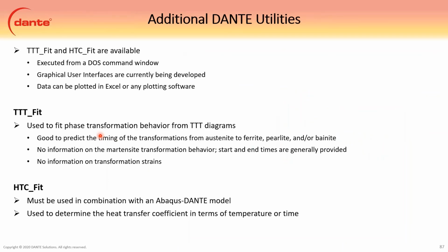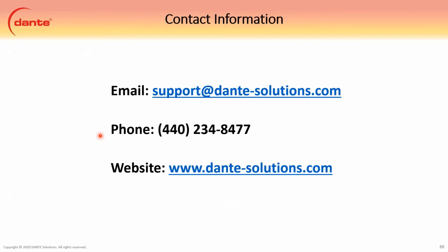Then we also have a TTT fit and a heat transfer coefficient fit, which use TTT diagrams to fit the phase transformation behavior, and then HTC fit uses thermocouple data to fit the heat transfer coefficient. Both of these are currently being worked on as far as graphical user interfaces go. So they're still available. Everything just has to be done through a command window and applied in Excel right now, but they're on their way.